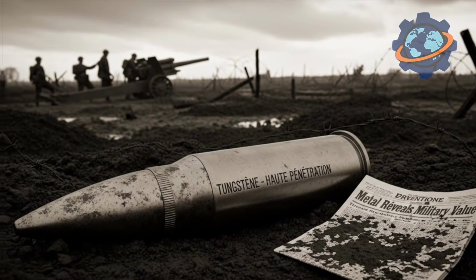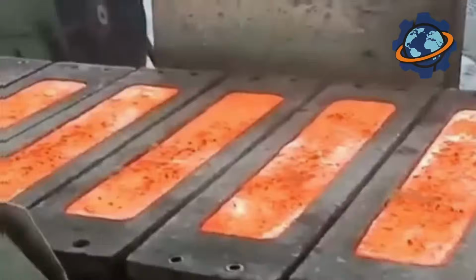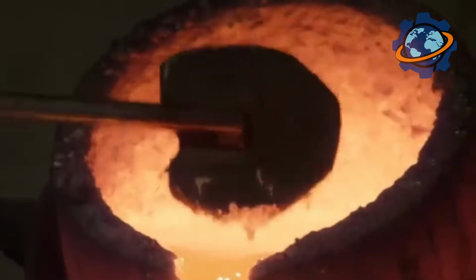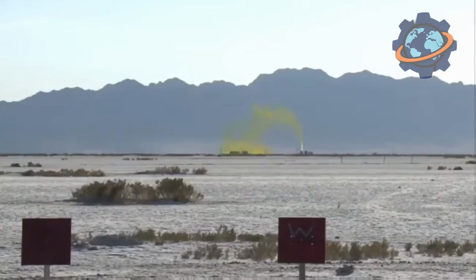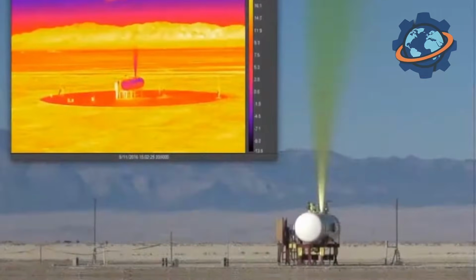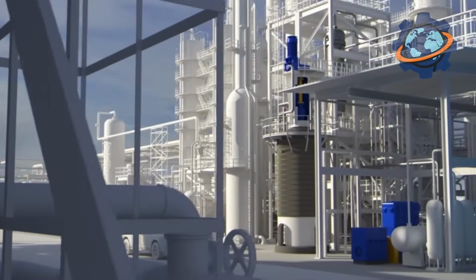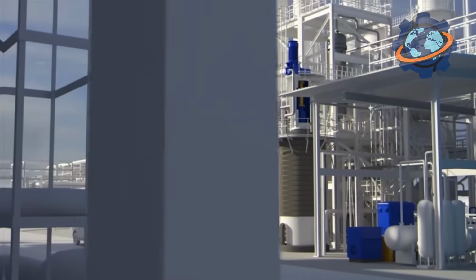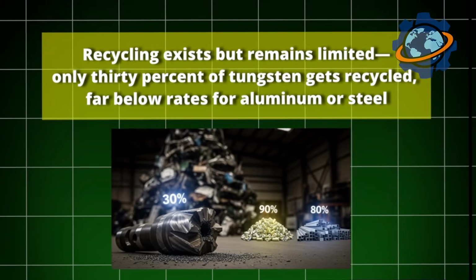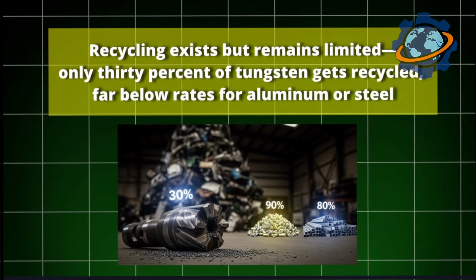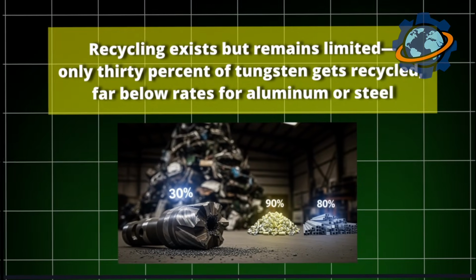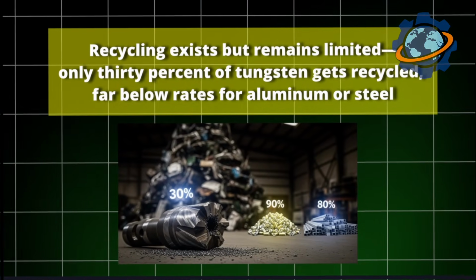Today's annual production exceeds 90,000 tons, with China dominating supply chains so completely that Western nations consider tungsten a strategic vulnerability. Carbon emissions remain problematic as tungsten production generates 8 tons of CO2 per ton of metal, primarily from energy-intensive processing. Recycling exists but remains limited. Only 30% of tungsten gets recycled, far below rates for aluminum or steel.